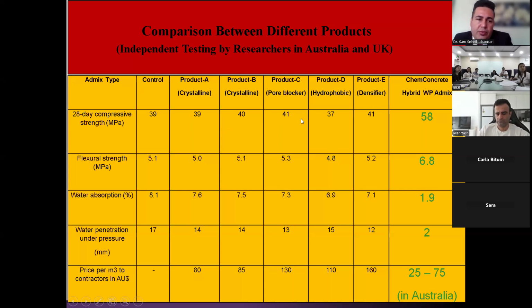You can see the 28-day compressive strength of control or untreated concrete was 39 MPa. For the first crystalline was 39, second crystalline was 40, for pore blocker was 41, for hydrophobic it was 37. For the densifier, it was 41, but with our product, it was 58 MPa. In all these conditions, the highest dosage recommended by the suppliers were used. You can see a similar trend was observed for flexural strengths.